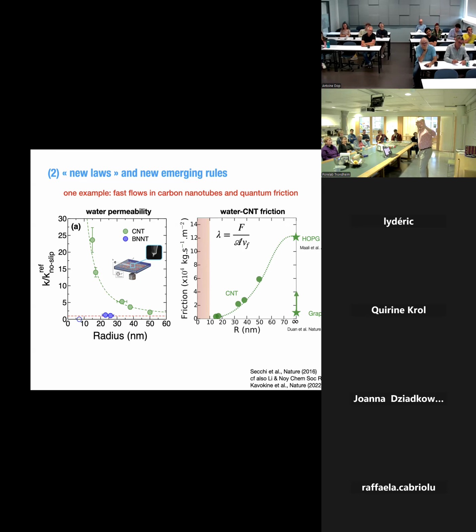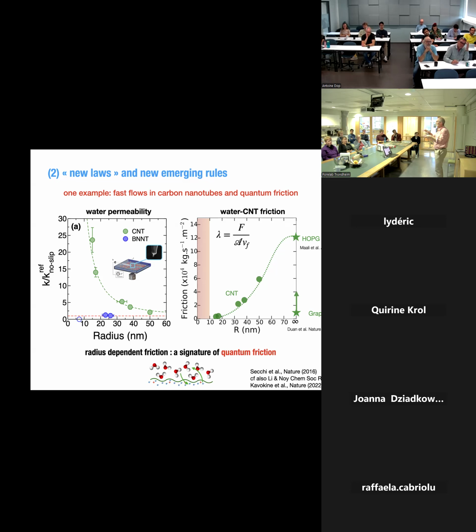I have no time at all to enter into this, but what we suggested, in work with Marie-Laure and a great student at the time, Nikita Kavokin, was that it was a signature of quantum friction. It's quantum, meaning that the water, which has partial charges, couples to the electron flux in the system. And you have electronic dissipation. So it's really a many-body effect. And we could explain this kind of curve versus radius. I will skip more discussion.